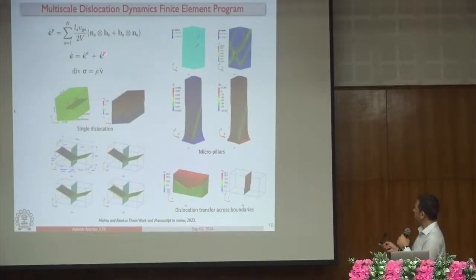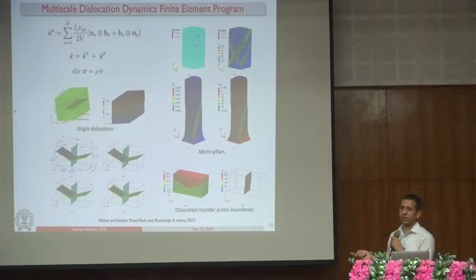Now, this plasticity business also does not happen at continuum scale. As you may be aware, it is happening because of line defects, dislocations, or because of grain sliding, or because of, let's say, vacancy movement, high temperature plastic deformation because of creep, right? So to understand that, we have this open source parallel framework, which is called Multi-Scale Dislocation Dynamics Finite Element Program, again developed by one of my students. In fact, one of the first PhD students who graduated now works for Micron.